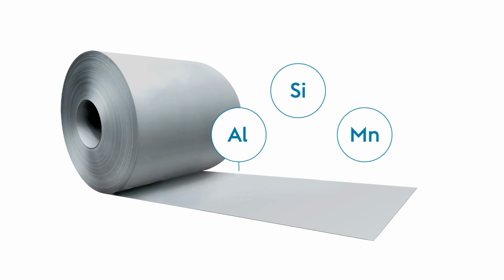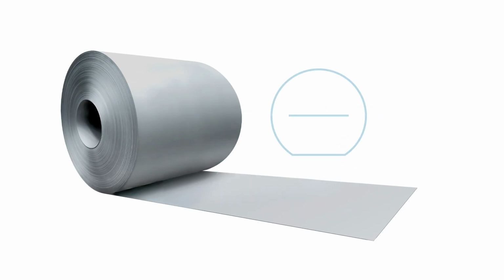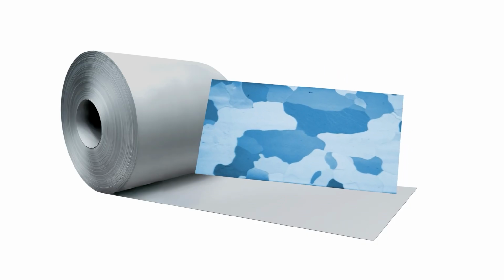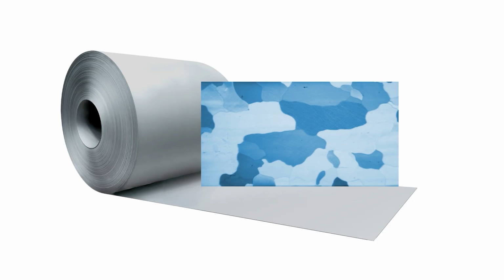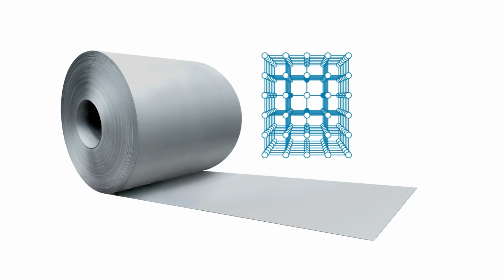Measures include proper use of alloys in the electrical steel and achieving the correct thickness. Special annealing processes are used to achieve optimum orientation and grain sizes in the crystalline steel grid. We avoid non-metallic inclusions and defects in the lattice structure. This means that our dipoles have less resistance when they are aligned. This all doesn't sound very spectacular, but it is a science that our specialists at voestalpine have mastered.